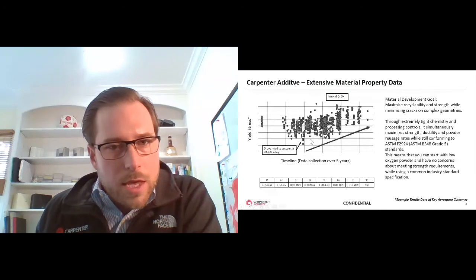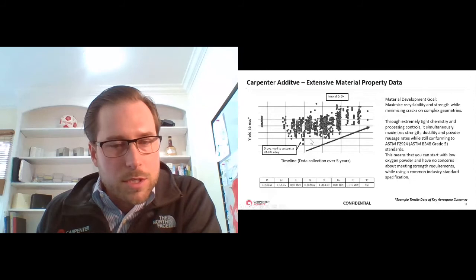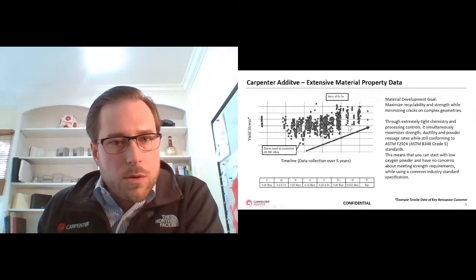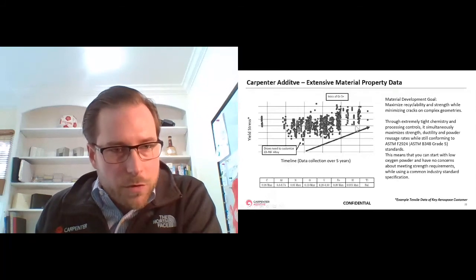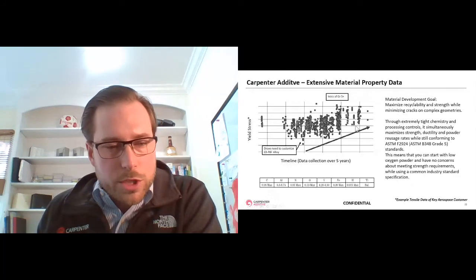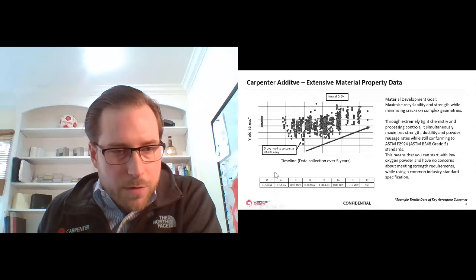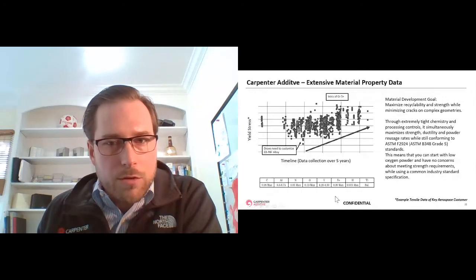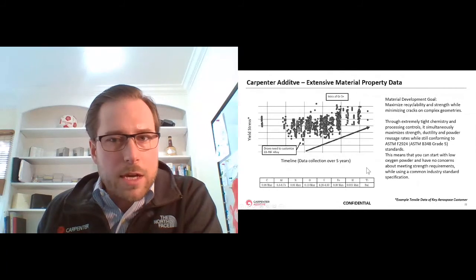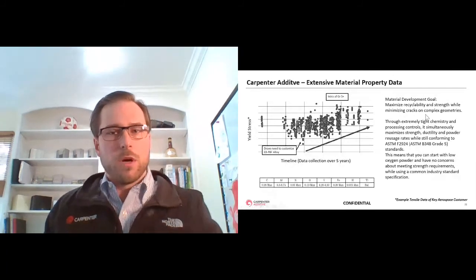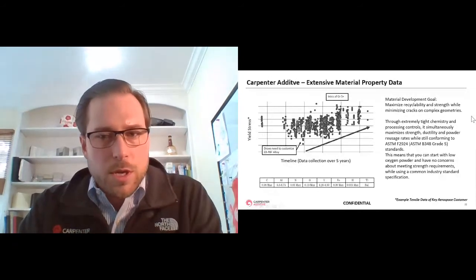And then here, this is where we introduced our grade 5+ titanium material. And what you can see is that there's a jump up in your yield stress in the material. So what that enables is it enables us to have the confidence to recycle the material more should we wish to. And this is the specification that we have for our grade 5+ material. And really our goal was to maximize our recyclability and strength while minimizing cracks on complex geometries.